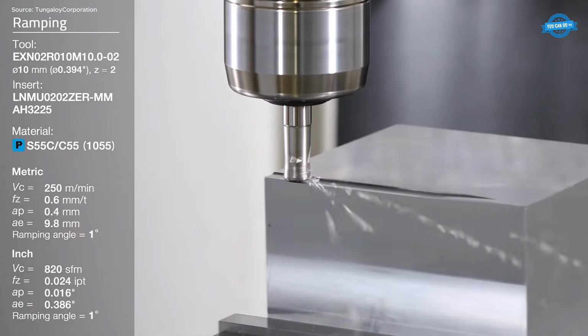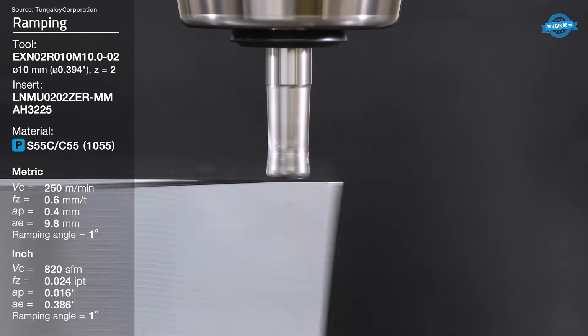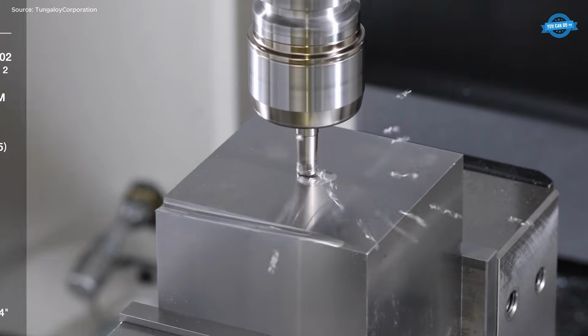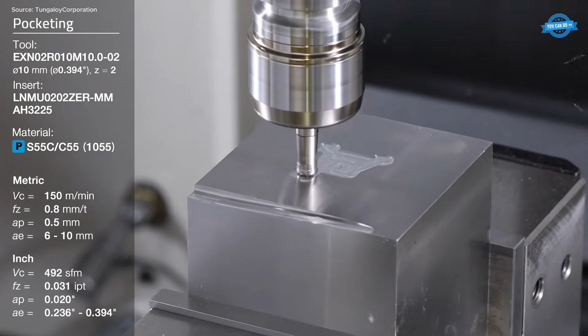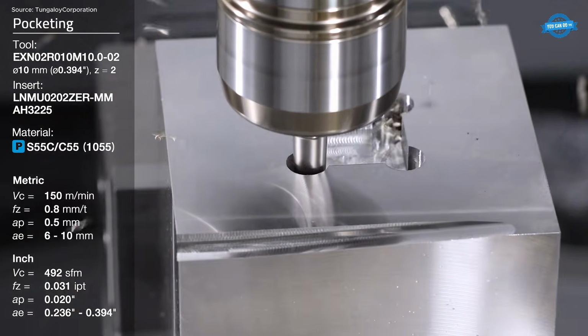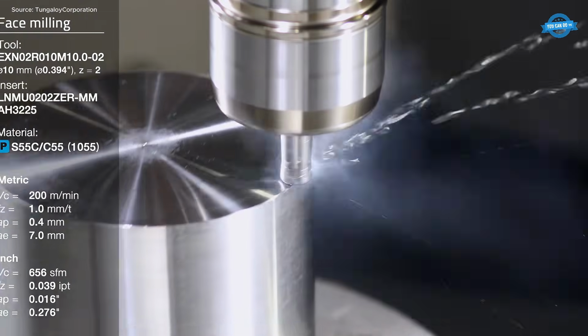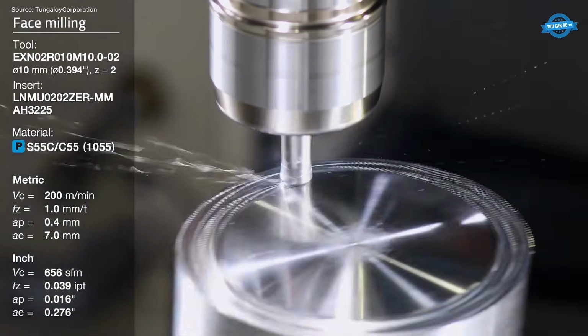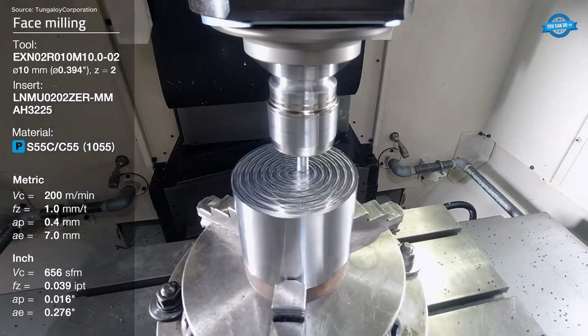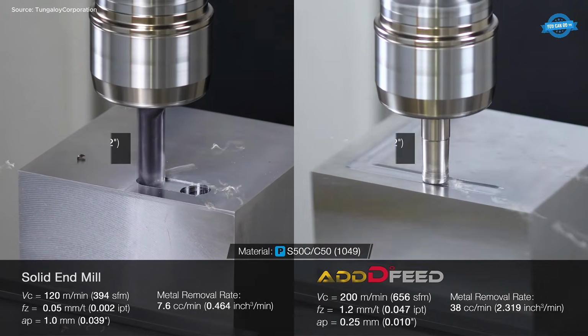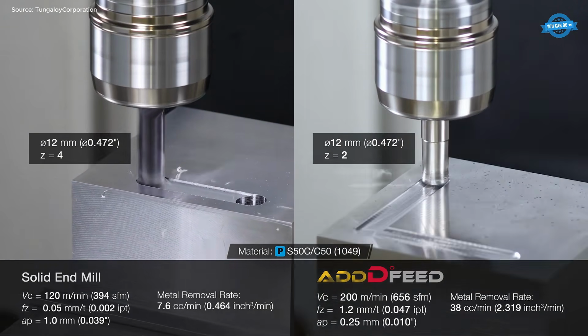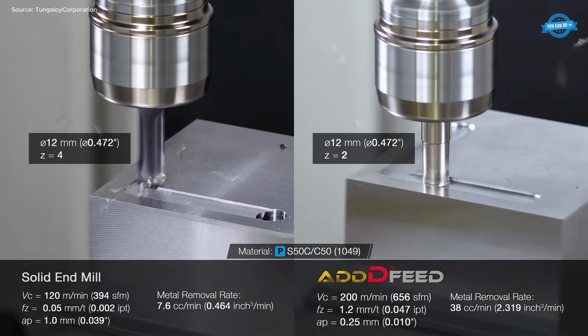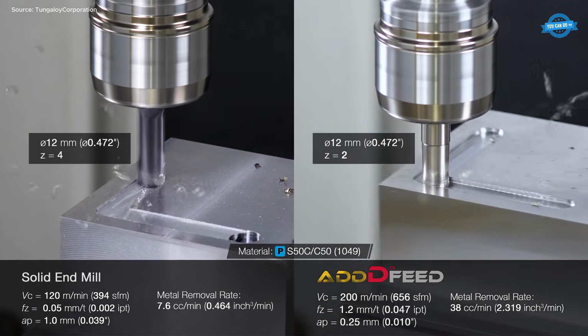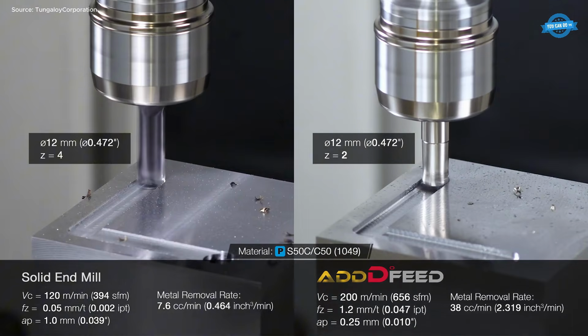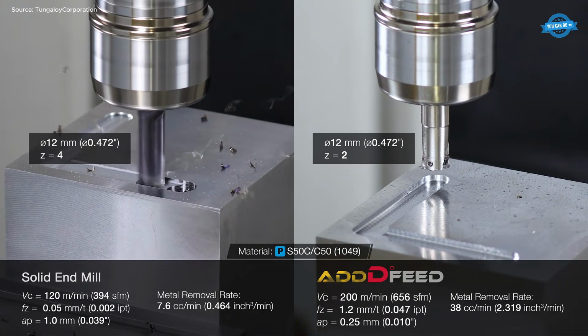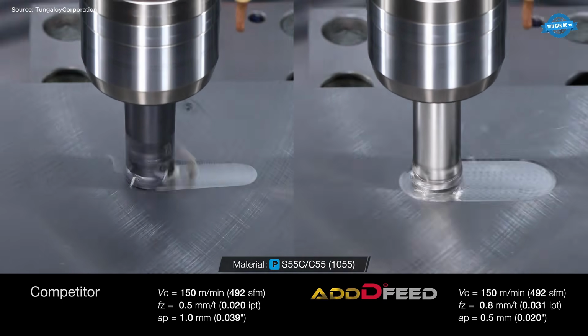AddDFeed is a high-feed milling solution optimized for small diameter tools from Ø8 mm to Ø25 mm. It supports LNMU 02, 03, and 06 inserts, offering cutting depths up to 1.5 millimeters. Ramping tests using a Ø10 mm tool with an LNMU0202ZER-MM insert achieved 250 meters per minute cutting speed and 0.6 mm/T feed with a 1-degree angle.